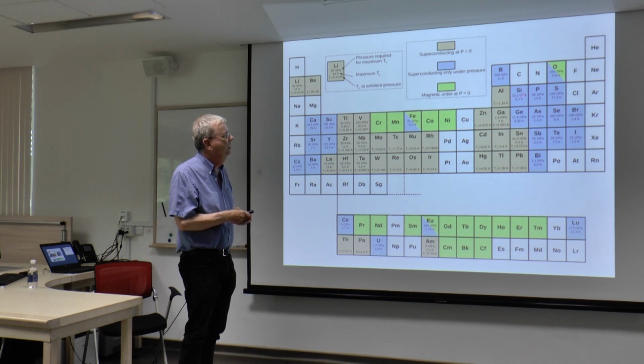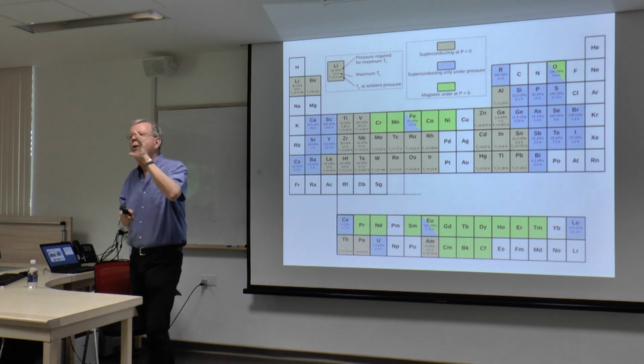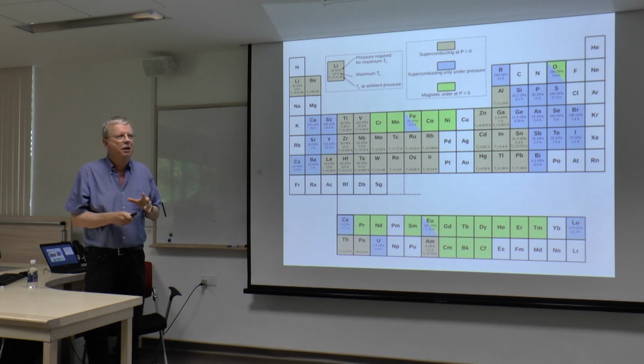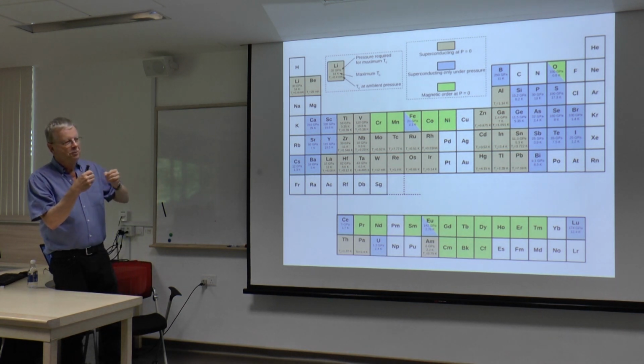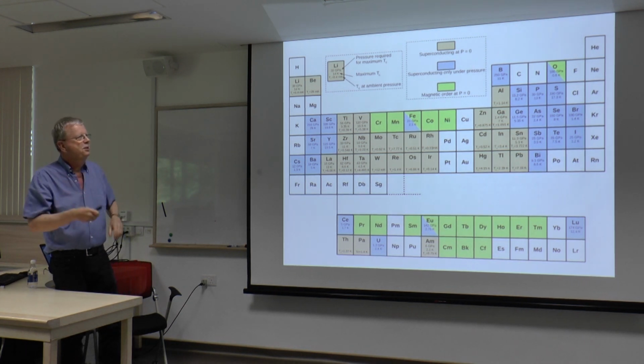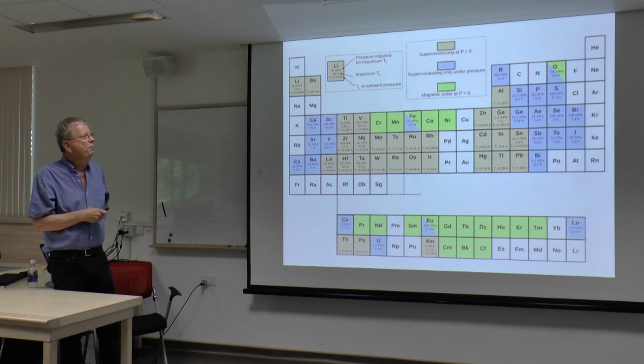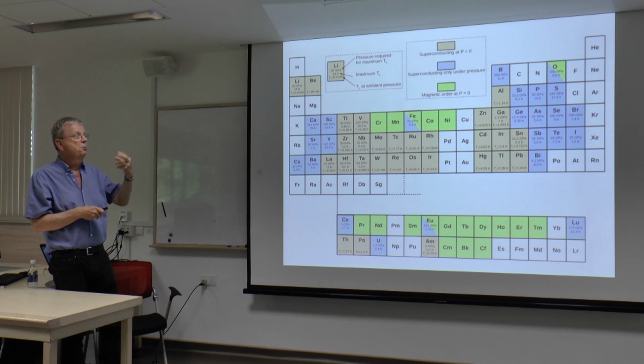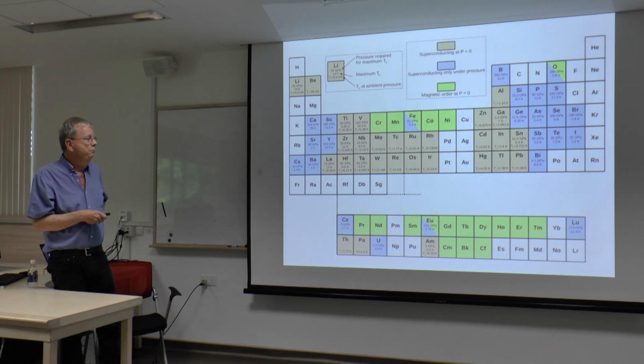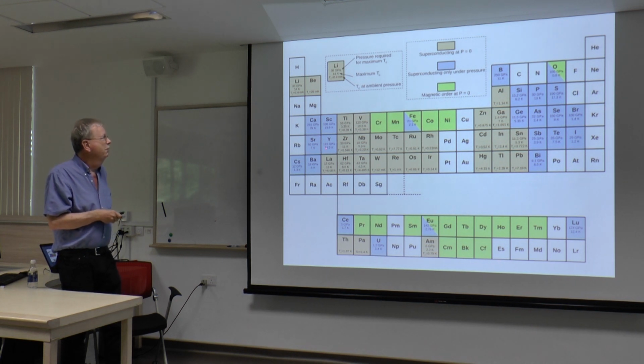At 15 GPa, it superconducts at 8.2 Kelvin. So actually after Matthias died, they used to compete with each other at meetings and claim each other had said something wrong. After Matthias was gone, silicon was experimentally proven to be a superconductor under pressure. Now, of course, it's a cheat. It's no longer the diamond structure. It's another structure. But anyway, some of these numbers are really out there.